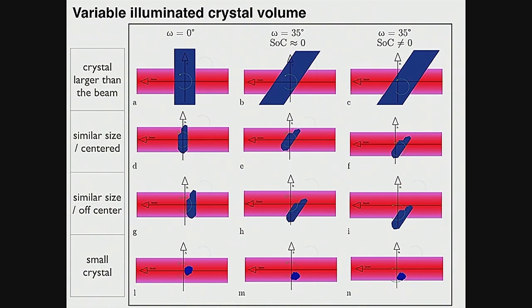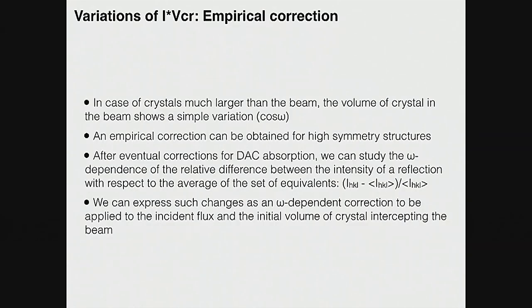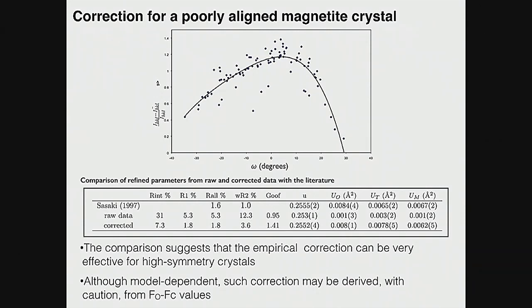And you, as a user, might not be able to put your crystal exactly in the beam, and so you're multiplying the sphere of confusion with your beam, and things move away. And of course, it's all dependent on the crystal size. If it is large, just filling the whole sample chamber, you have a simple omega correction with the rotation angle. If it is smaller, you might not be able to have a simple correction. So what can you do? You can have empirical corrections based on the variation of the intensities of peaks that supposedly should have the same intensities, and derive a fit curve through your actual data and correct for it.